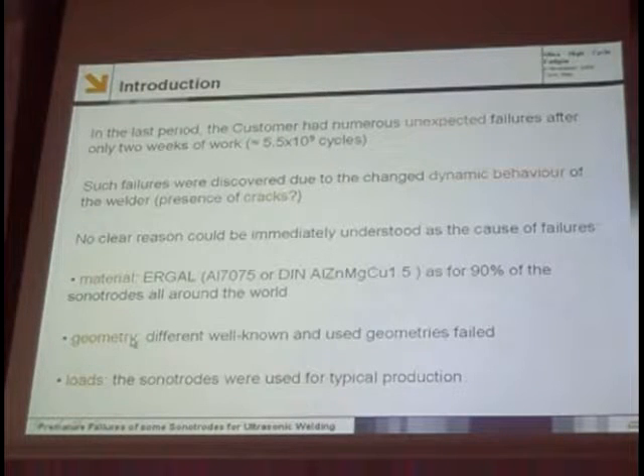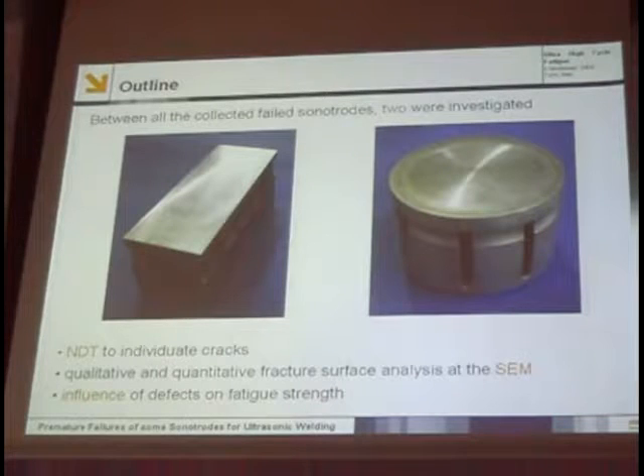The geometries of the returned sonotrodes were typical geometries, so nothing new from this point of view. And also the service was absolutely nothing special with respect to typical working conditions. Among all the sonotrodes that were returned, we chose two of them with quite different geometries: one square sonotrode, one circular.